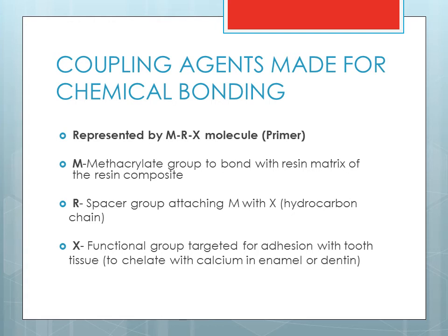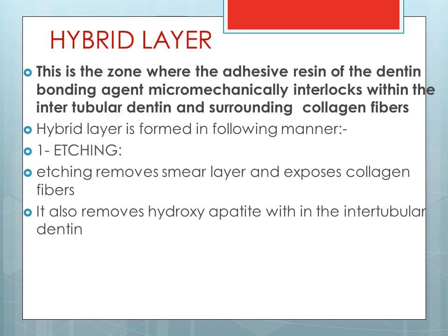The X is the molecule on the opposite side of the M, and this is the functional group which is targeted for adhesion with tooth tissue, to chelate with calcium in enamel or dentine. So the M bonds to the methacrylate group, and the X bonds to the tooth structure and chelates with the calcium present in the enamel or dentine. And this is called the MRX molecule, which is basically the primer.